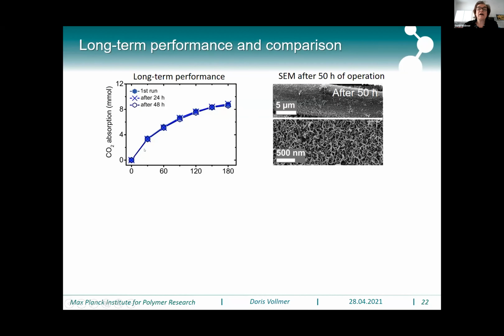Then we quantified the carbon dioxide uptake over time, and after approximately 2-3 hours, depending on the volume of our amine solution, we observed a saturation. Even more important, even after 50 hours of continuous operation, we did not observe a change in adsorption efficiency. That is supported by SEM images. After 50 hours, the surface looks unaltered.